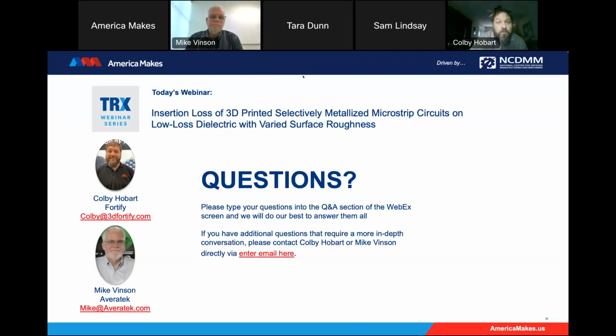So if your goal, though, was to really characterize and make the difference in metal roughness as inward facing toward the ground really stand out, you would want to develop on the thinnest dielectric you could. And also that would allow you to characterize up to higher frequencies. So we noticed during testing that our frequency limitation for the measurements, it got noisy between 10 and 20 gigahertz, but above 20 gigahertz, there was some moding there, and that kind of made the results above 20 not very valid.